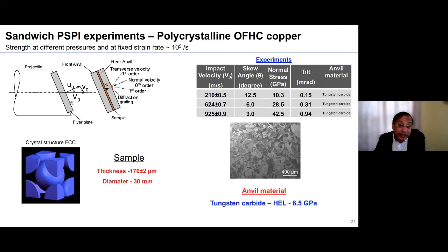It's 170 microns in this case. Of course, we know the crystal structure for the material copper is FCC. So the thickness of the sample is 170 microns, and the diameter, which is limited by our gun, is about 30 millimeters.